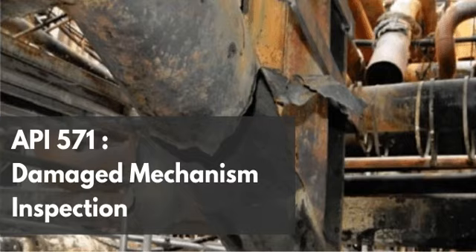Well, a failure analyst relies heavily on those specific morphologies. When you slice open a failed pipe, polish it, etch it, and look through the lens, seeing that intergranular spider web in a carbon steel weldment immediately points you toward an environmentally assisted cracking mechanism. And if ammonia is in the process stream, you basically have your primary suspect. Exactly.